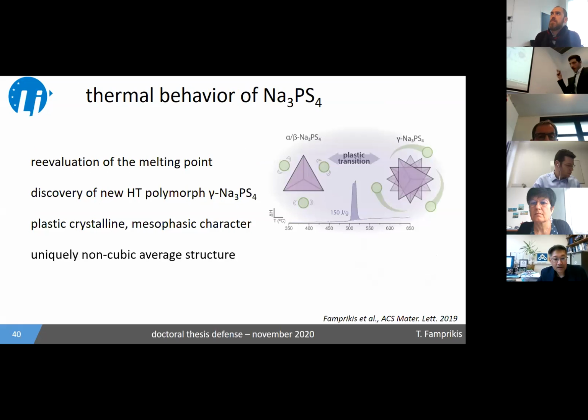A sort of question open to discussion that I pose here is that this FDDD space group that we observe is quite unique. Most of the other phases in the literature that show similar characteristics, rotational disorder, and so on, actually crystallize in maximal cubic symmetry, Fm3̄m. So what is the deal with FDDD is an open question that I would love to discuss with the jury